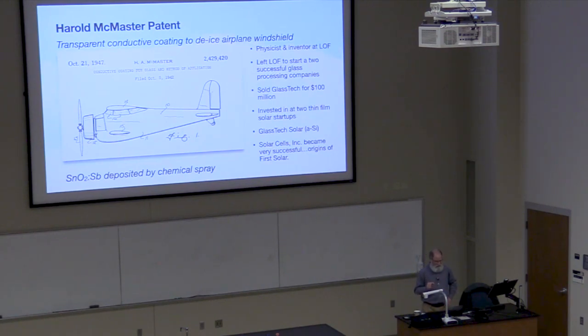So, in the 40s, Harold McMaster was a physicist and an inventor at Libby Owens Ford. And he came up with this coating on glass. This is at a time when aircraft were starting to fly high enough that they needed pressurized cabins, and the glass could develop ice from the cold temperature. So he did this work, filed the patent in 1942. It was not published until after World War II. And it was a process for making antimony-doped tin oxide by chemical spray on aircraft windshield.